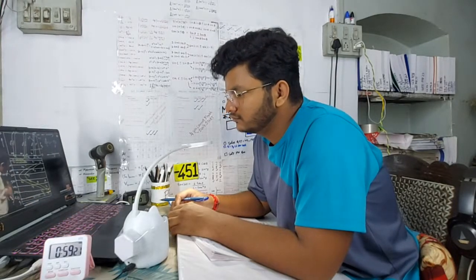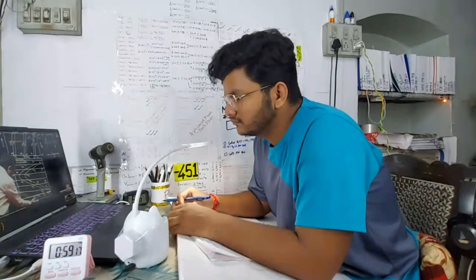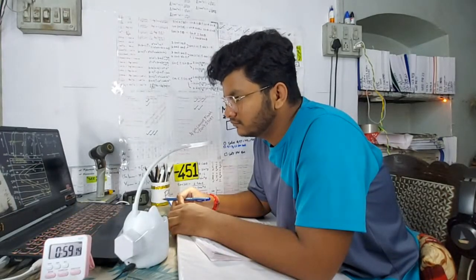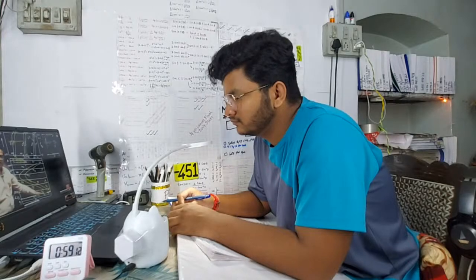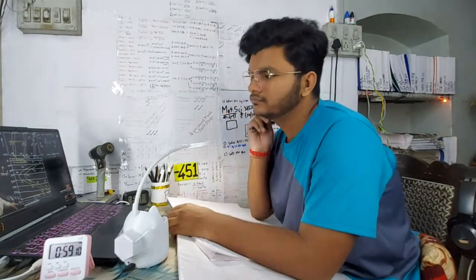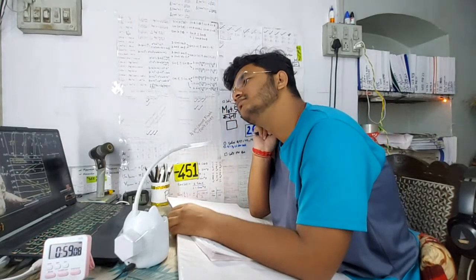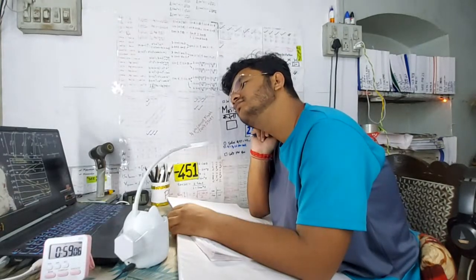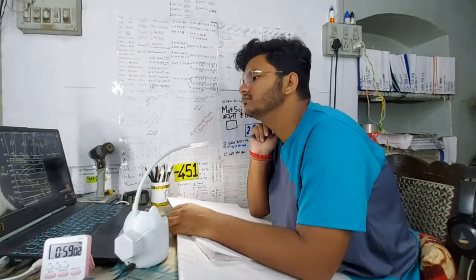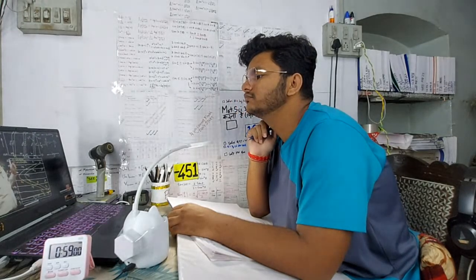और MF टेम्परेचर के नीचे कौन रहेगा? No retained austenite. Even retained austenite will get converted to martensite. So इसके नीचे रहेगा martensite. Right? Martensite formation begins here. And if MF temperature is here, above MF temperature, you are always going to have retained austenite along with the martensite. Below MF temperature, you will have only martensite. Point is clearly defined. Now, this diagram is what is called TTT diagram.